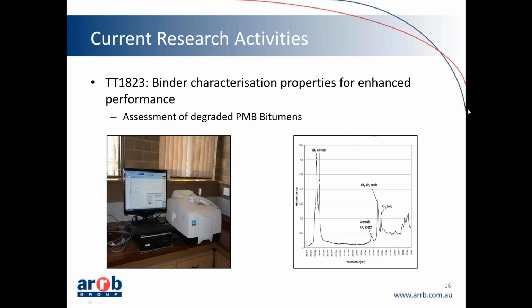Another aspect of this was because we were degrading the binder by heating after we blended it, we wanted to do a little bit of an assessment. We did 2 assessments. The one that we did in my laboratory was an FTIR, which is a Fourier Transform Infrared Spectrometer, which you can see in your left picture. We did an analysis of each of the polymer modified binders over the various stages of degradation to see whether or not we could see any change in the spectrum.